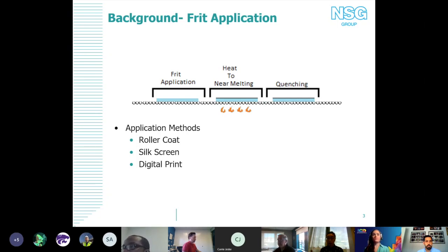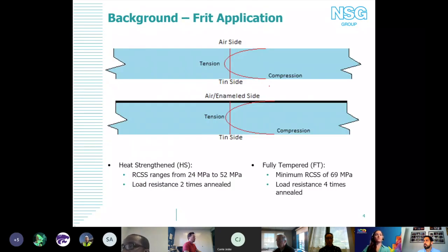whenever it's rapidly cooled, the ceramic frit is now fused onto the surface of the glass. So they're now one cohesive element, and it can't be scratched off. What this does, and this is something that happens whether it's fritted or not, when it goes through the tempering oven, you essentially are creating this residual compressive surface stress in the glass, and that's what determines whether it's heat strengthened or fully tempered.